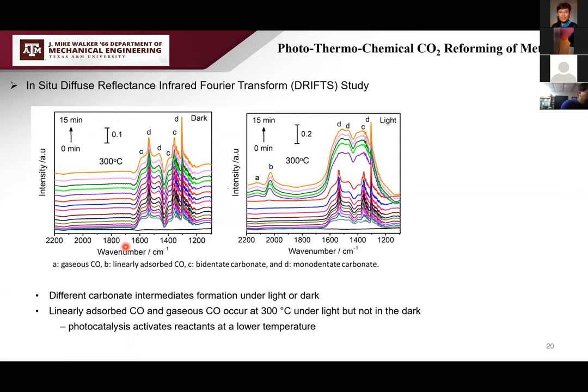To confirm this hypothesis, we used in-situ DRIFT to study surface properties under real reaction conditions at 300°C — at higher temperatures the spectrum is too weak. Under dark conditions, species look one way; under light, after 10 minutes the carbonate adsorption peaks are different, and additionally linear-bound CO and gaseous CO are observed only under light, not in the dark. This proves that photocatalysis really activates reactants at lower temperature.